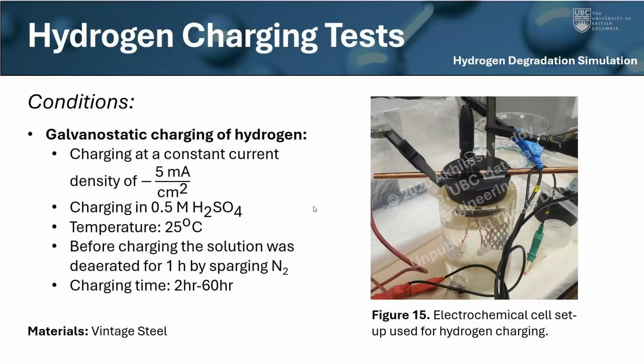And so initially, in order to simulate worst case hydrogen degradation, I didn't really expose that steel to hydrogen sulfide. In research, we can accelerate our conditions. And so what I did was I applied a negative current and I forced hydrogen evolution reactions to take place by generating hydrogen on the surface of the steel. And I did this for various samples and I changed the charging time. So I charged steel between 2 hours and 60 hours. And this, of course, changes the concentration of hydrogen within the steel.